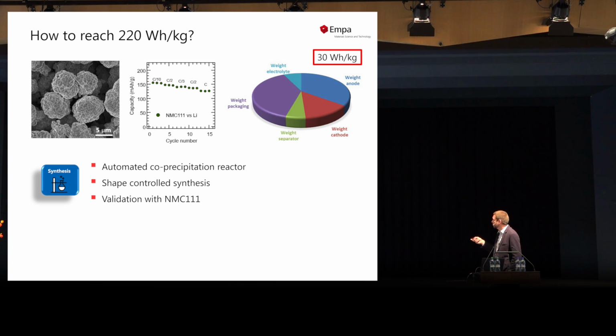So C over 10 means charging and discharging the battery in a period of 10 hours, and then at faster C rates here, this is only 1 hour charge and discharge. You can see we lose a bit of capacity. That is typical for battery materials, but our materials are comparable to what is available from industry.